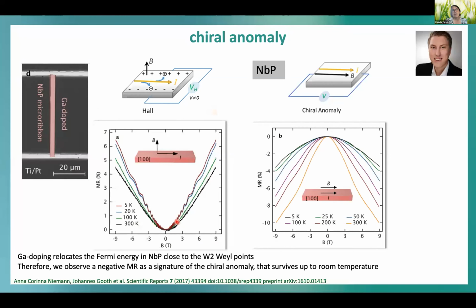So this was then doped with the gallium to the Fermi energy. And the idea here was now to check the chiral anomaly by changing the direction of the current.